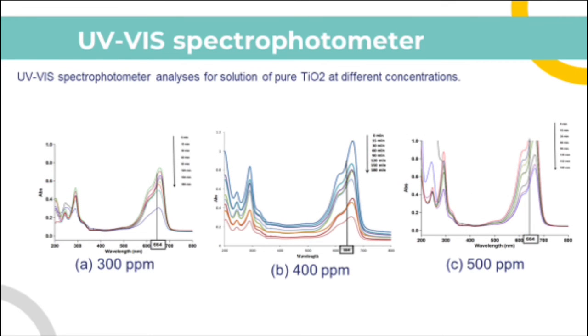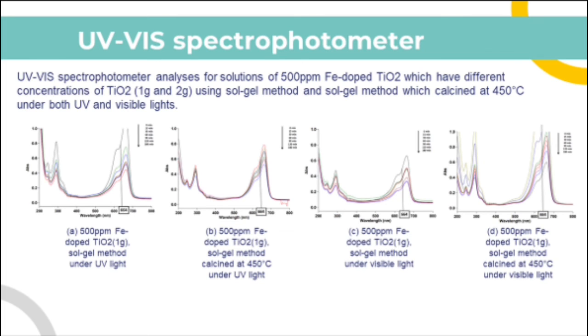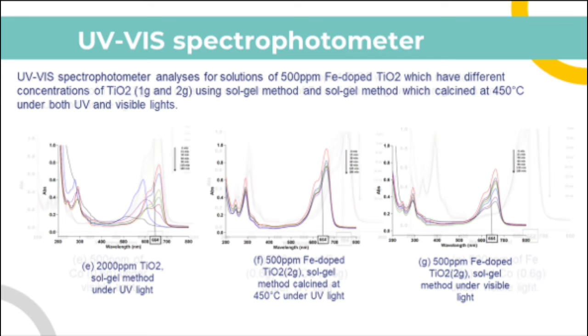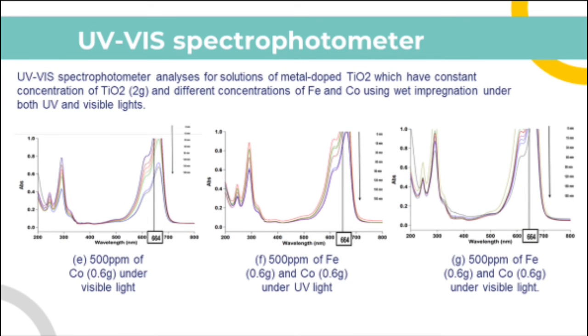And here we show the absorption of methylene blue in solution with pure titanium dioxide at different concentrations every 30 minutes under UV spectrophotometry, and the reflection spectra of all Fe-doped titanium dioxide using the sol-gel method, calcined at 450 degrees Celsius, under both UV and visible light. A shoulder appears at around 664 nanometers. These graphs show the absorption of methylene blue in solution samples, and this graph presents the absorption in solution samples of Fe-doped titanium dioxide using the wet impregnation method, also the absorption in solution samples of cobalt-doped titanium dioxide using the wet impregnation method. In addition, the absorption in solution samples of Fe and cobalt doped titanium dioxide using the same method. These samples were taken under both UV and visible light.